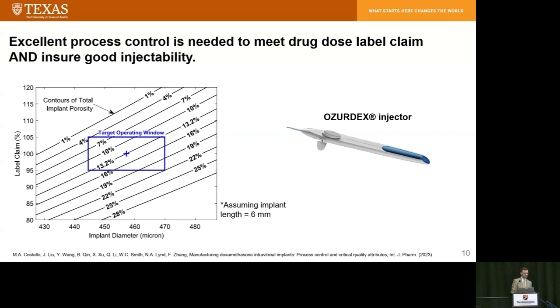Another big factor here on the process control is that the implant has to have a smooth surface and also have a fairly regular diameter, actually an extremely consistent diameter, over the whole length of the implant, such that it can slide out of the Ozurdex applicator correctly during the intravitreal injection.